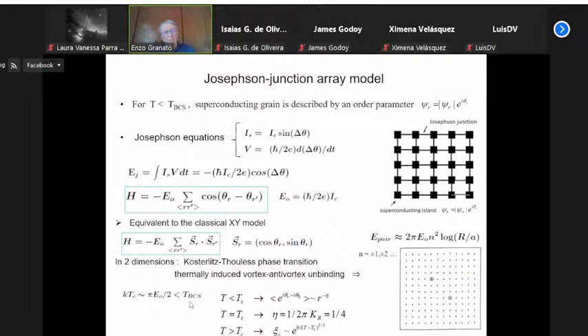This transition happens since the transition depends on the coupling between the spins, and this coupling is by itself connected to the critical current for the junction. The critical temperature for the Kosterlitz-Thouless phase transition in this system is below the critical temperature at which the grains become superconducting. So this transition therefore describes the phase coherence between the grains, which are both below the transition of the grains themselves. Between these two transitions, the system has a finite resistivity.